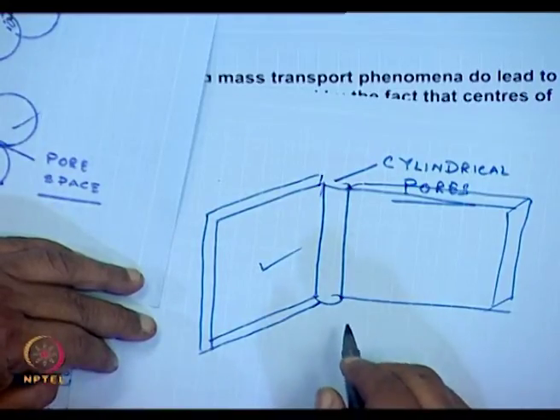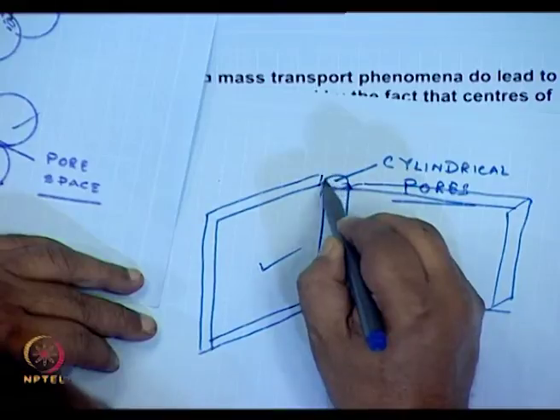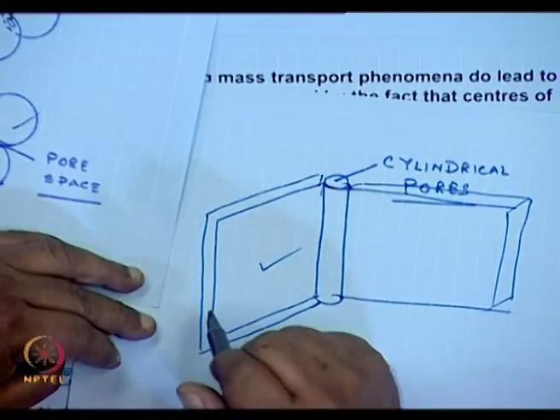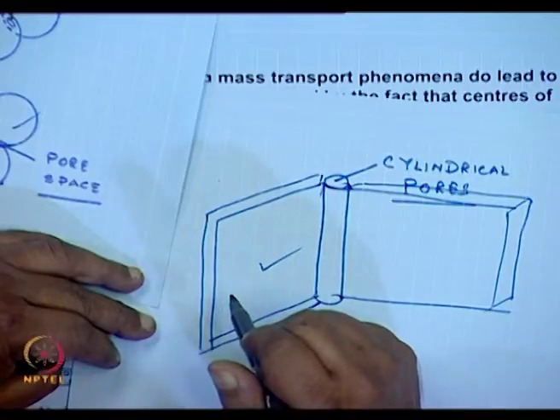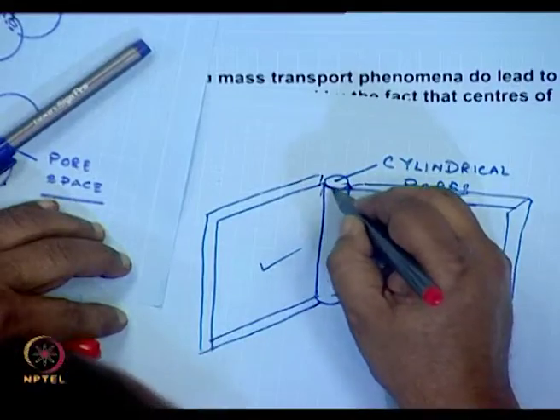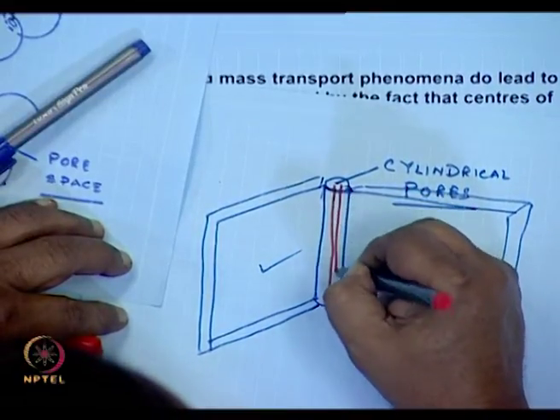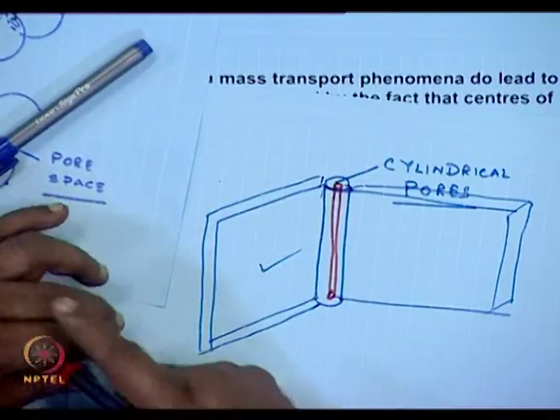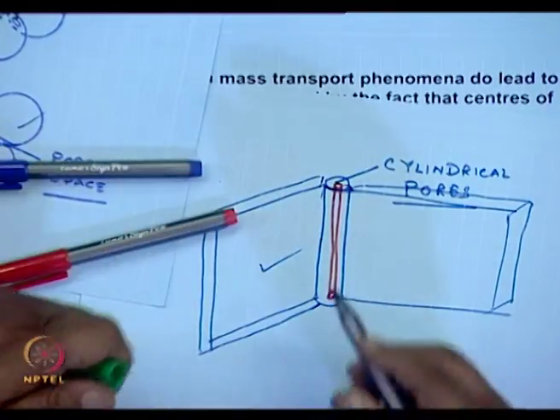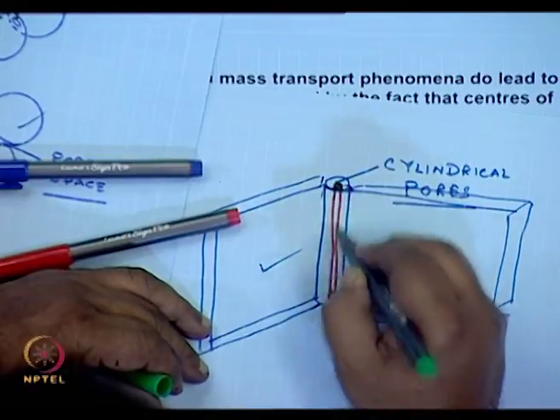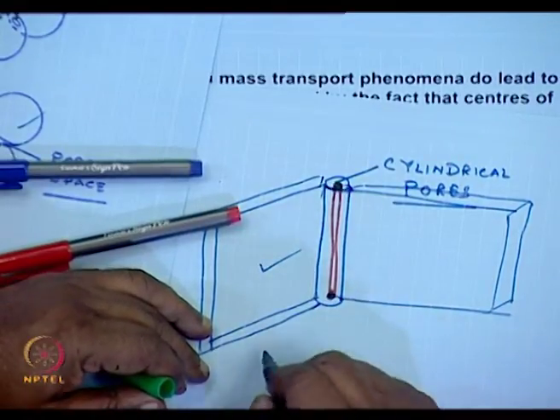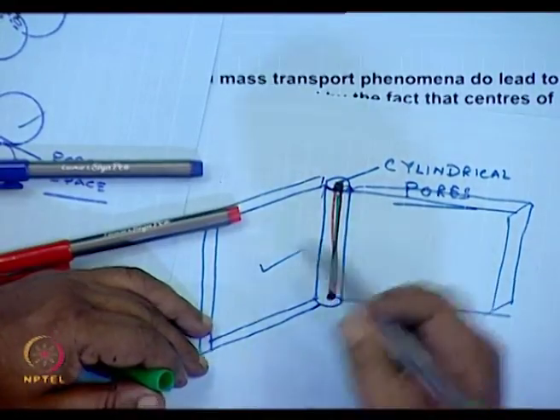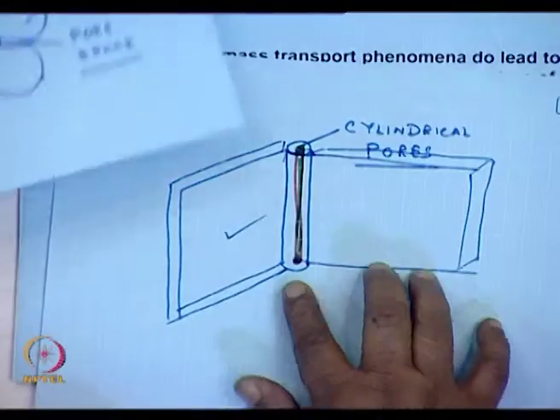Now what happens is, since this is a cylindrical pore, the vacancy concentration will decrease. So mass diffusion will occur, and as more and more sintering occurs, the size of this cylindrical pore decreases till finally they become so thin that the pores are isolated at these ends, leaving a simple grain boundary.